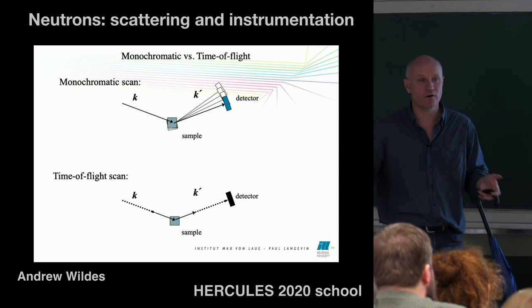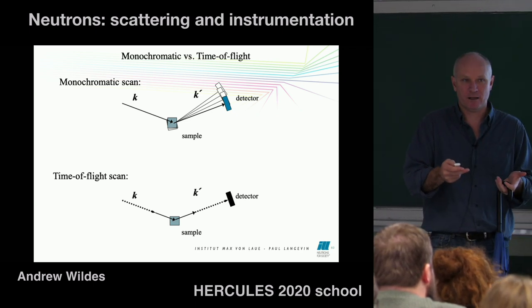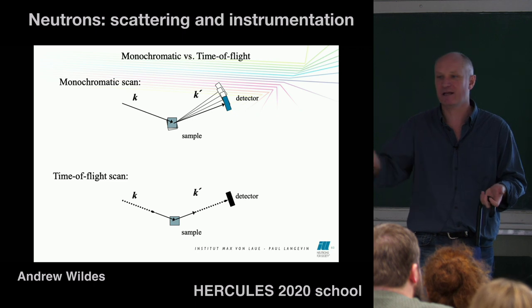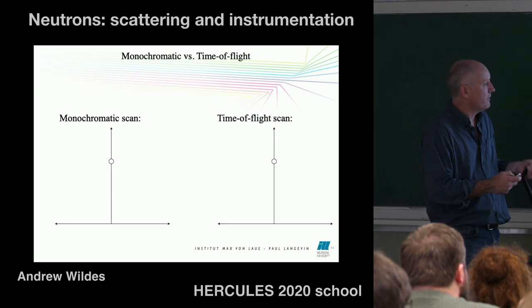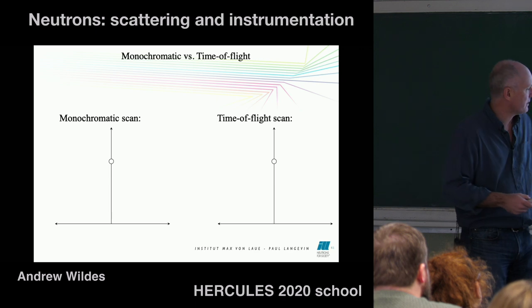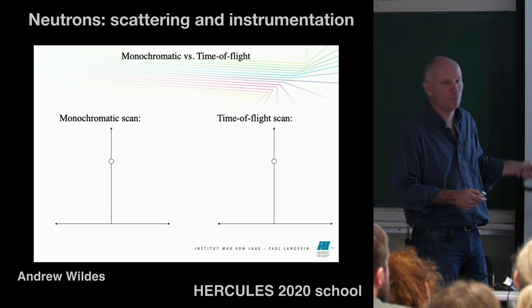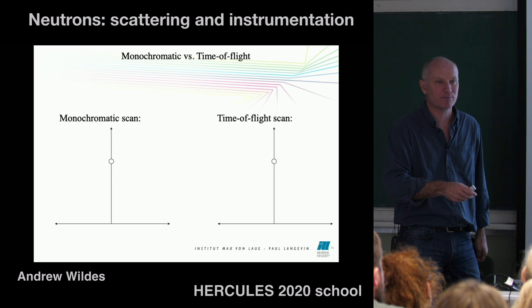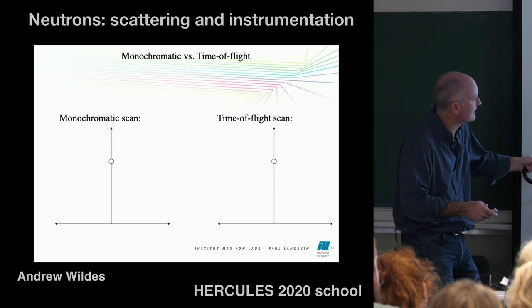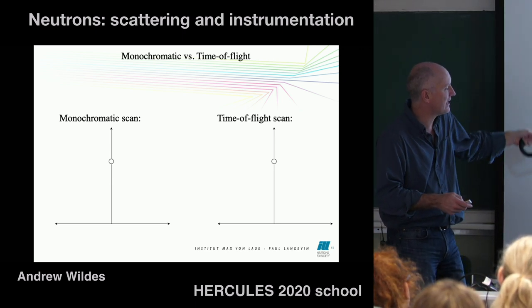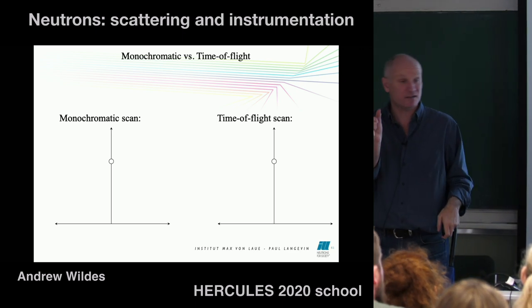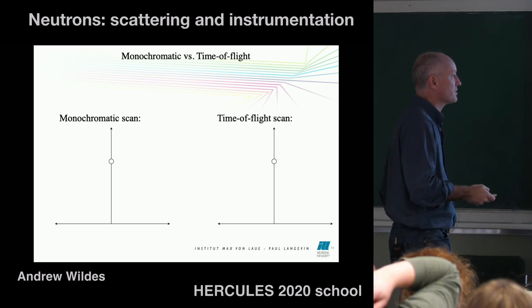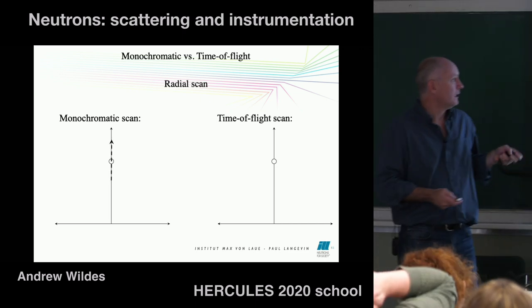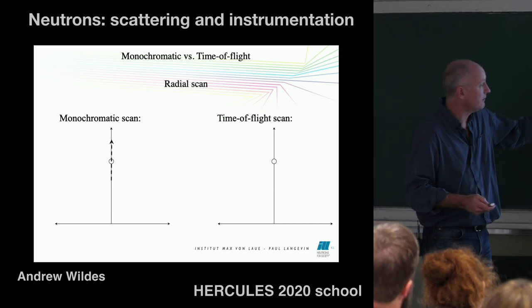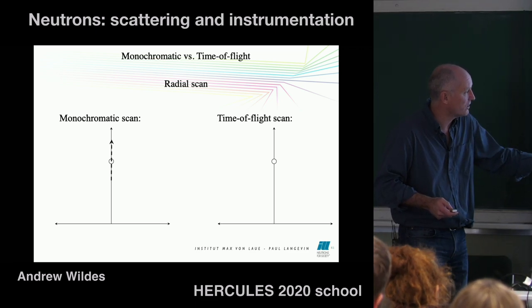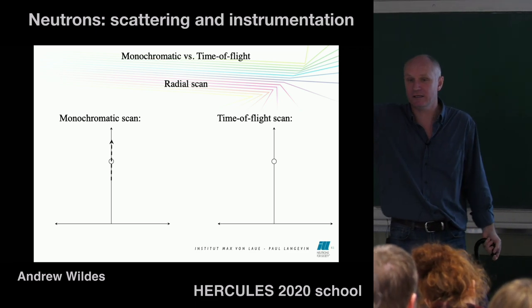All right, now let's imagine that you wanted to do an experiment to measure a Bragg peak from a single crystal, right? So this is a picture of what that might look like in reciprocal space. You have reciprocal space, you have this point here, which is a reciprocal lattice position, that's where your Bragg peak is. And let's imagine that you wanted to do a scan along that direction. You do a scan along that direction, it's going to tell you something about the d-spacing of your crystal. So if you wanted to do that in a monochromatic scan, I'm going to call that a radial scan, right? Because this here, that's my origin in reciprocal space, and that's a radial trajectory from the origin.